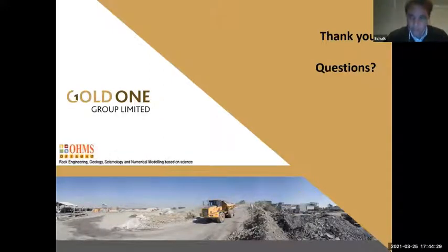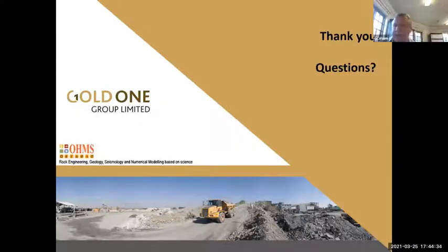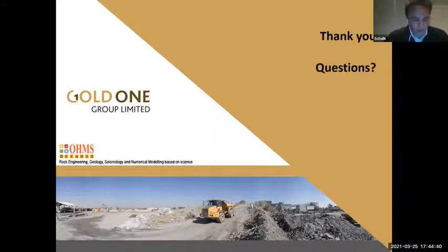Okay. And then Johan's question was the stitching issue. How did the stitching issue get solved, or is it still an ongoing challenge? No, it got solved because they folded the bags on the corners, not folded it double, but folded it back on itself. So you have 4 layers then, and then they used a heavier material on the stitching as well, and I think the stitching pattern also changed on the bag, which increased the strength of the stitching to a point where we no longer have issues with it.